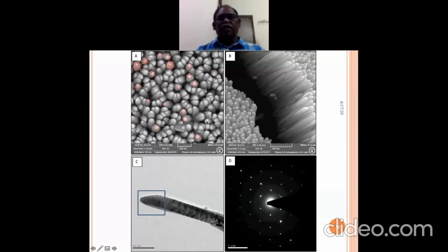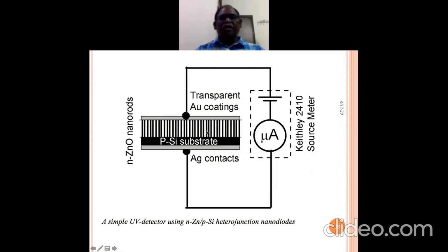And then this is the device. So you have the p substrate. These are n-type ZnO nanorods, and this is for contact. We have a gold coating over here, and this silver contact we have again for this contact. And then you shine this with UV and you will find photocurrent.